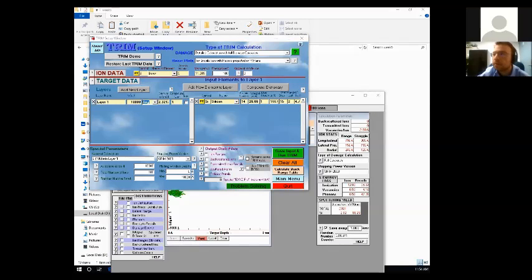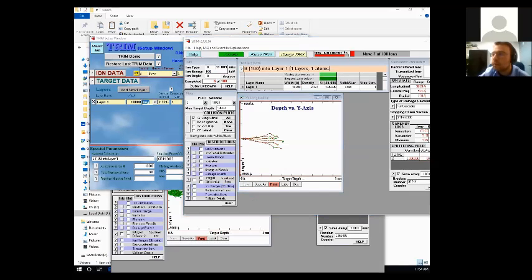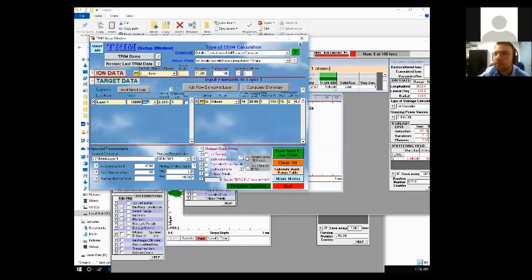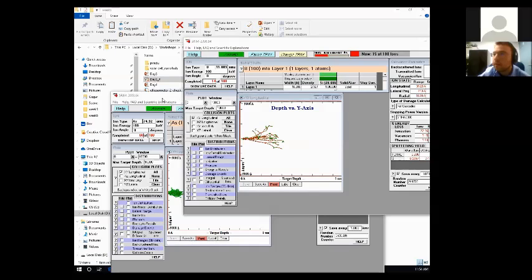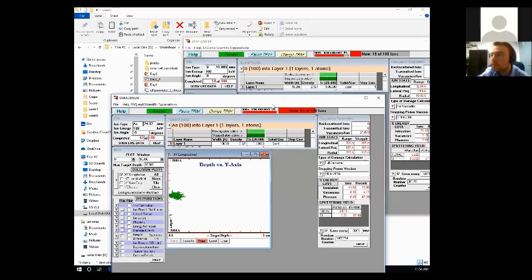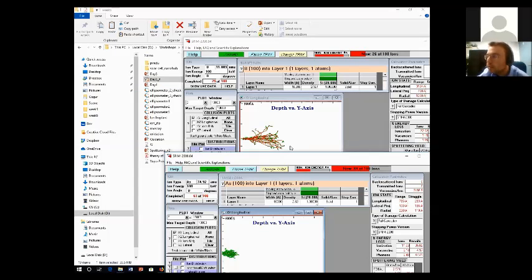Yes, so this is the drastic importance. What is so different between the two? Okay, I hope you guys can see the difference clearly. Boron is only giving us the damage towards the end of its range, towards the stopping point. When it loses energy, then it starts to interact with the crystal all of a sudden.